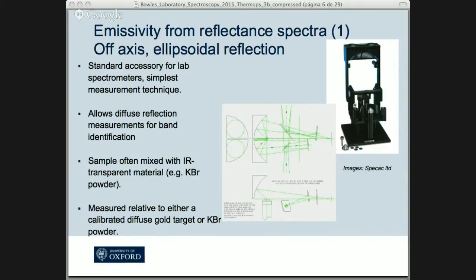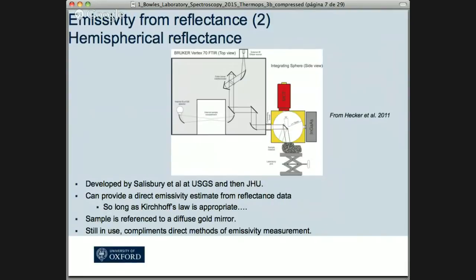People often mix samples up with potassium bromide powder, and this isn't just for the kind of porosity stuff that you've heard about from the Vincent et al. type work. It's also because you want to improve your signal to noise performance. You don't want to saturate some of your bands. And then you measure it relative to either a gold target, which you've had calibrated by a national standards lab or equivalent, or just potassium bromide powder, and you apply scaling because potassium bromide has no spectral features to speak of really. That kind of works, but has some serious deficiencies, which I'll explain in a minute.